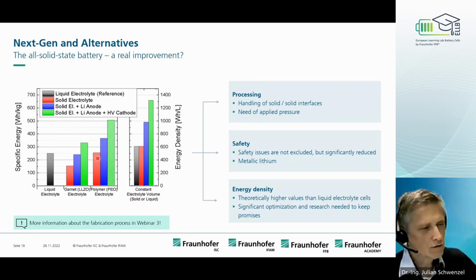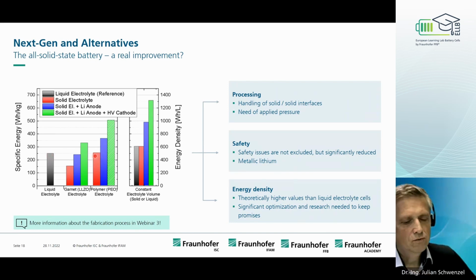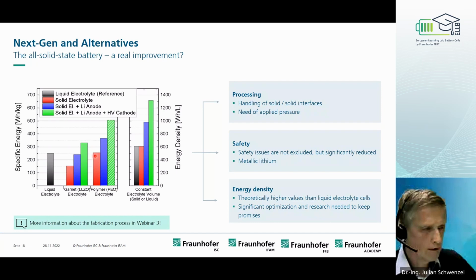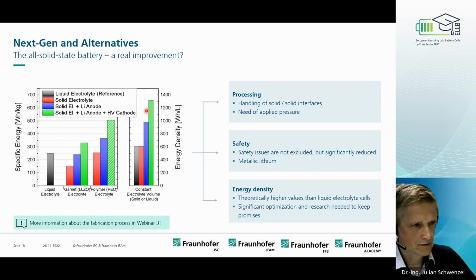The same calculation was done with a polymer. A polymer electrolyte was used, and here you can see there's no change in the energy density. This is due to the density of this polymer, which is similar to liquid. And if we have a polymer which is also stable with lithium metal or with a high voltage cathode, we can improve the energy density of the system a lot. Also given here is the volumetric energy density, where there is a dramatic increase.